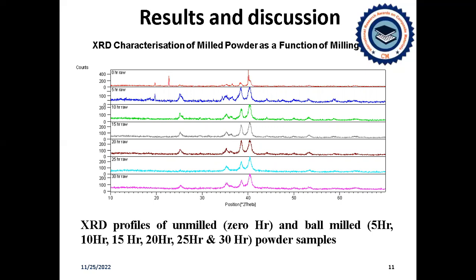We can observe that at the initial ball milling time, that is at 0 hour, the peaks are very narrow, which means it presents the crystallinity in the powder. As the milling progresses to 5 or 10 hour, 15, 20, 25, and 30, the peaks get broadened, and we can observe the shift in the peak, which is due to the alloying process between each of the elements.